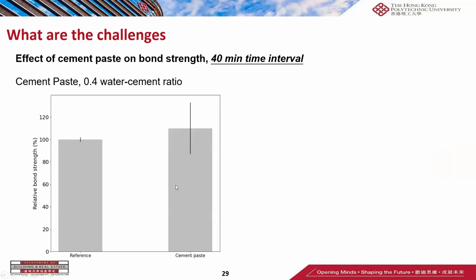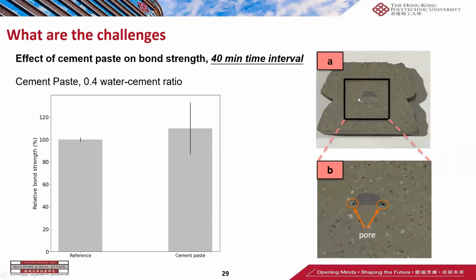So in this case, firstly, you can find the results regarding the mechanical performance. With the introduction of cement paste between the interface, the bond strength is increased only very slightly. This is because the cement paste cannot be evenly dispersed at the interface. And also in some cases, the cement paste will incur some big pores at the interface.